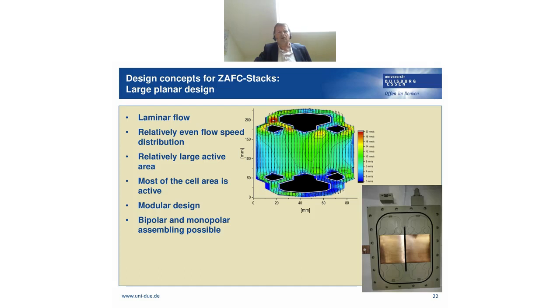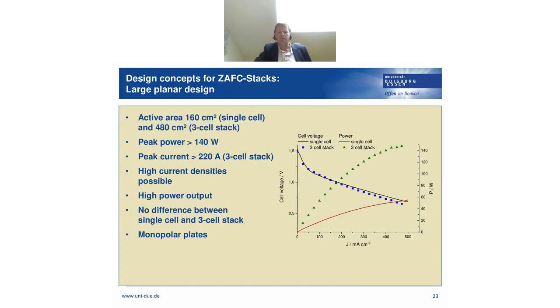So we use this modular design to build up a 3-cell stack with a 480 square centimeter active area, and the peak power was a little bit more than 140 watt, which you can see here. The power axis is on the right side, and the green triangles show the power for the 3-cell measurement. So high current densities are possible also in the stacks, of several hundred milliamps per square centimeter, and we did not observe a large difference between the single cell and the 3-cell stack performance.